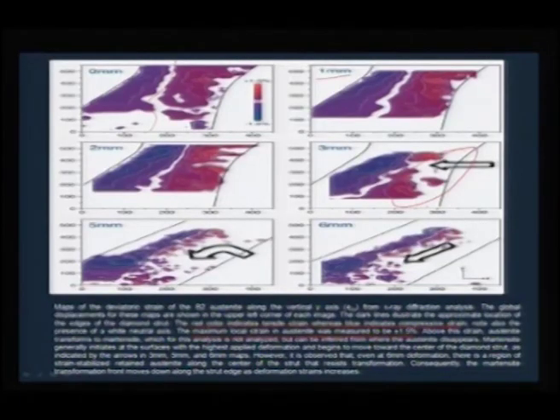Beyond a particular condition, it cannot be brought back to its original state. In other words, it loses its super elasticity. Therefore, this contour gives you an idea about the transformation limit, and that is what is mentioned here. However, it is observed that even at 6 millimeter deformation, there is a region of strain stabilized retained austenite along the center of the strut that resists transformation. Consequently, the martensite transformation front moves down along the strut edge as deformation strain increases. This is what we see here.